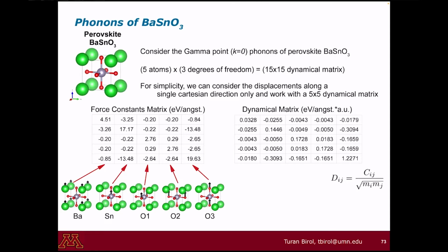So if I understood correctly, if you do one by one, you call it frozen phonons, but then what's the other option? The other option is using density functional perturbation theory. In VASP, that's IBRION equal to 8. So it does a perturbative expansion. Its implementation is a bit tricky, so I'm not getting into the details. But there also, you need to consider specific perturbations to your system and calculate your system's response to that. And again, most of the time, the perturbations considered are just individual atomic displacements. Okay, I see. So that's the more brute force method that doesn't take advantage of the space group representations.